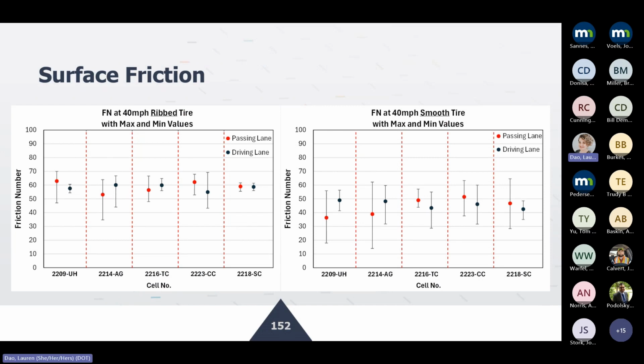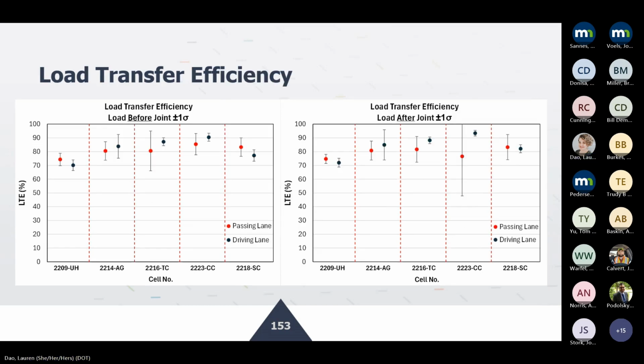Most of them, the rib tire and the smooth tire testing was performed. And you see most of these values hovering around the 60 range for the rib tire and the 40 to 50 range for the smooth tires. Again, like I said, we are more interested in looking at how these trend over time rather than the absolute values here. And load transfer efficiency was also performed, and most of them are in the 70, 80, 85 range.